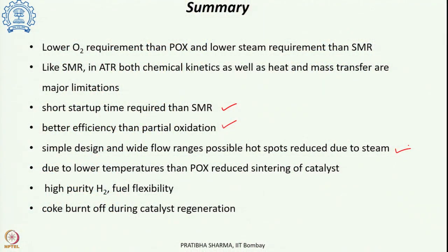The design of the autothermal reformer is comparatively simpler. There are different ranges in which we can produce H2 and CO. Various wide flow ranges are possible. At the same time, since we are using steam, the possibility of hotspot formation inside the reformer is reduced. The temperatures encountered in the autothermal reformer are lower than in partial oxidation, and as such the problem of sintering is lowered in the autothermal reforming process. And we can use other fuels also, and get high purity hydrogen. The coke which is formed can be burned off during the catalytic regeneration.